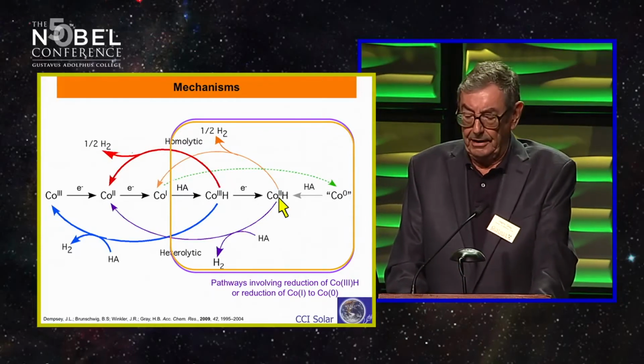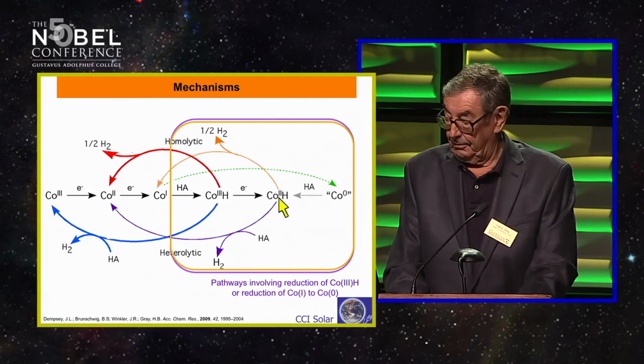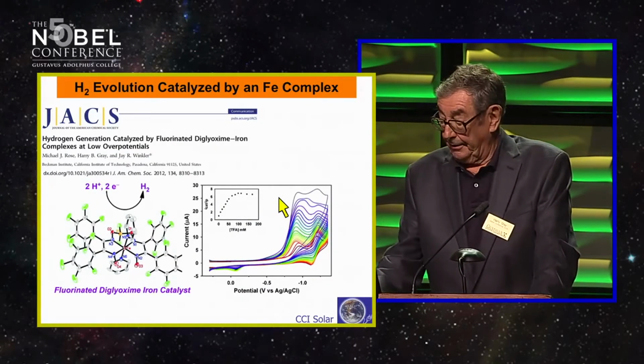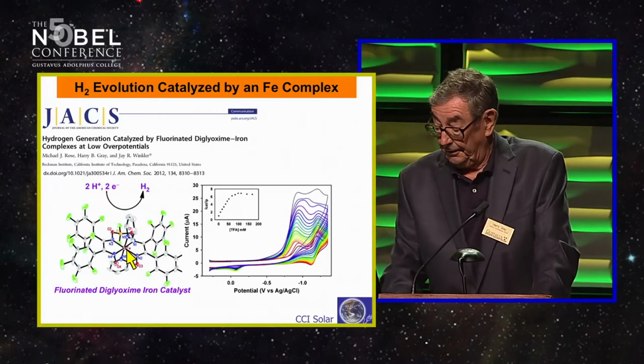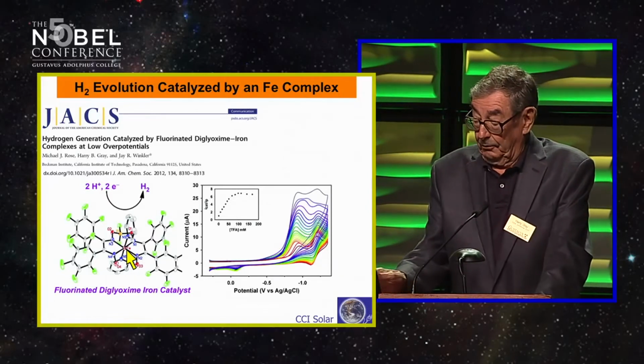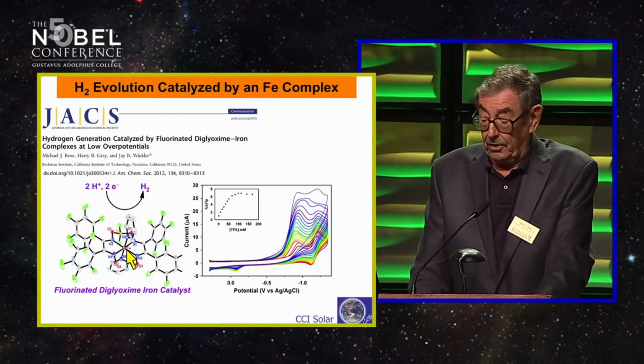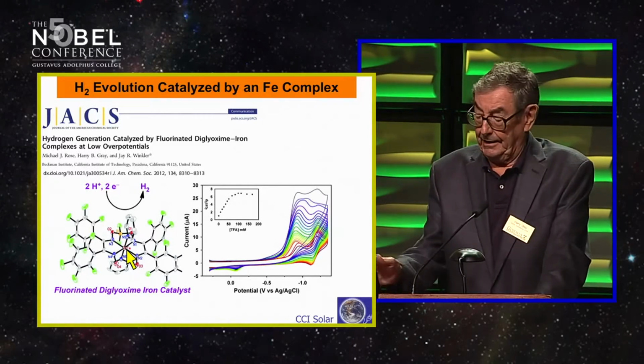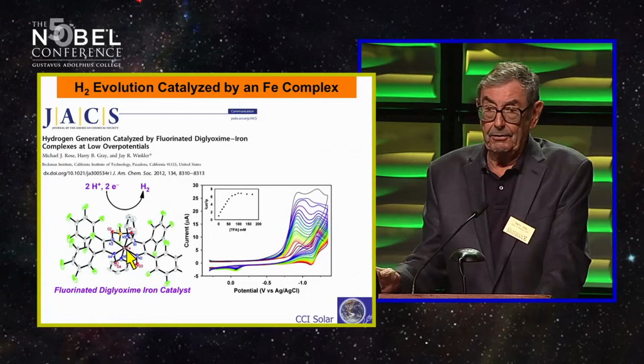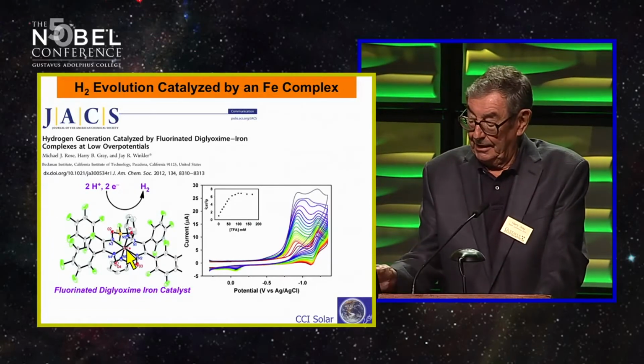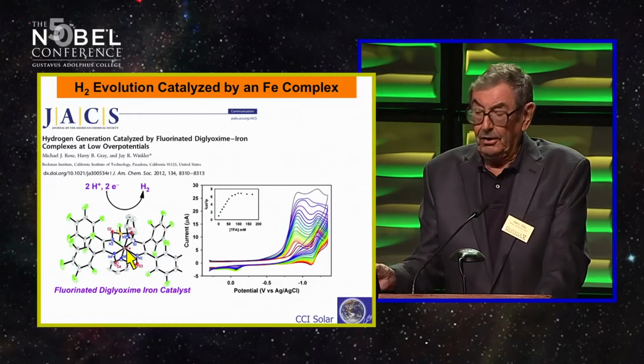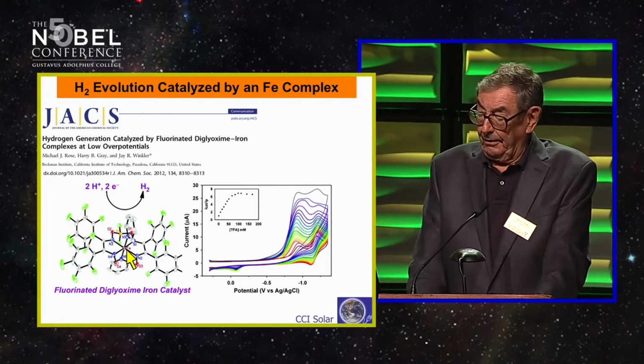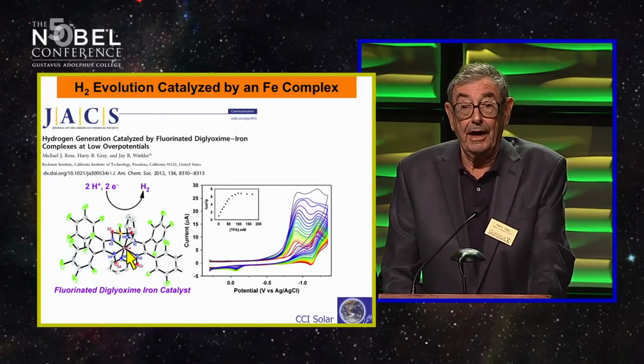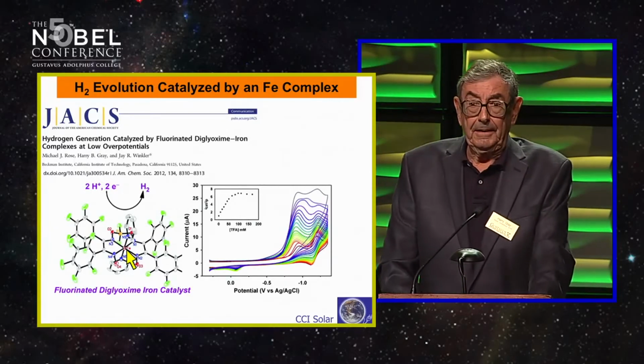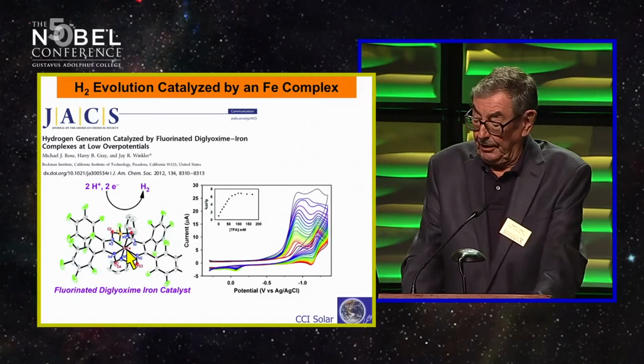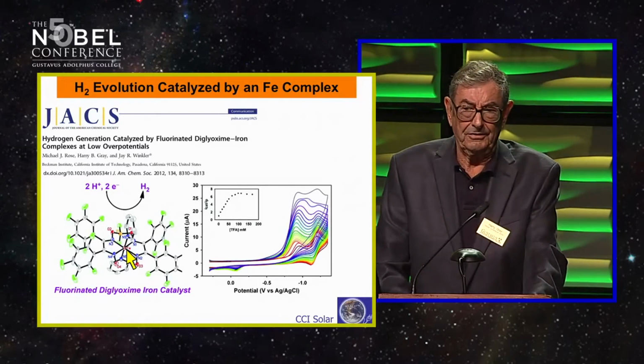So then, based on this knowledge, we designed the first iron catalyst, shown here, iron at the center. We put in these groups around it called ligands, heavily fluorinated, all sorts of fluorines, which allow us to add the extra electron we need into these ligands. And so we have now made a very, very powerful and active iron-containing catalyst that will evolve hydrogen at low potentials that we can incorporate in these devices.